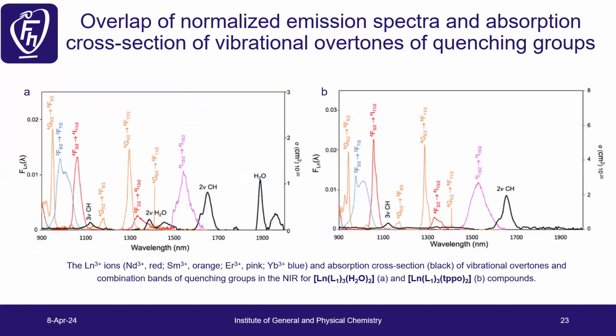And here I can show, so this is the tris complex, and this is the water-free complex. Here we can see the first harmonic of water, second harmonic of CH, second harmonic of water, and third harmonic of CH. We can see that for erbium we have more overlap of the second harmonic of CH and second harmonic of water. For samarium, which is orange, and neodymium, red, we have the second harmonic of water and third harmonic of CH groups. And in blue is only shown the ytterbium, and you can see that we have only the third harmonic of CH. That's why we see a different trend in ytterbium compared to erbium, samarium, or neodymium.